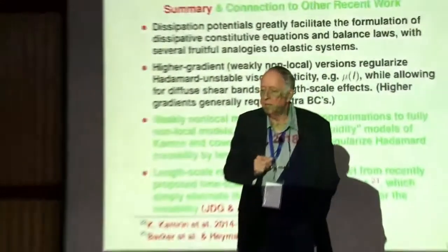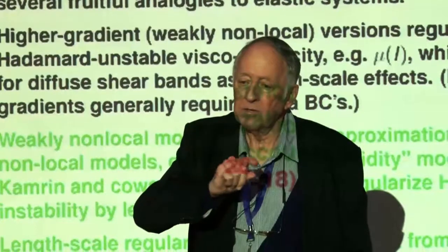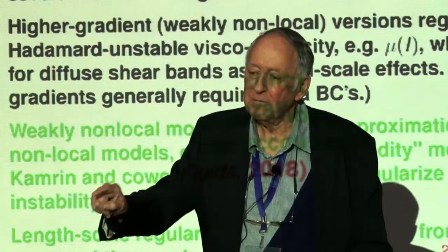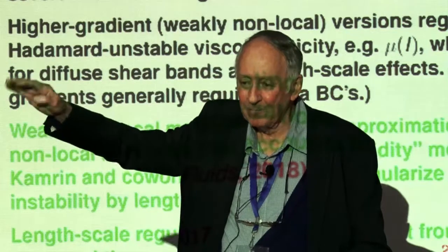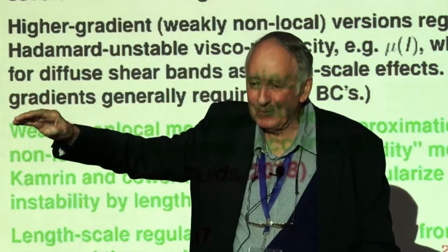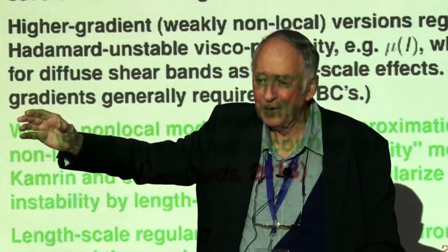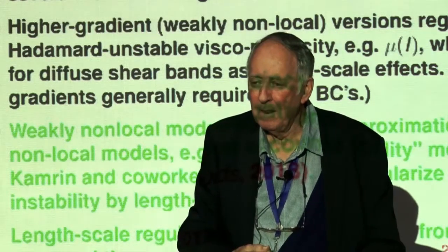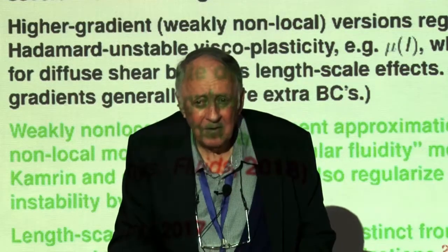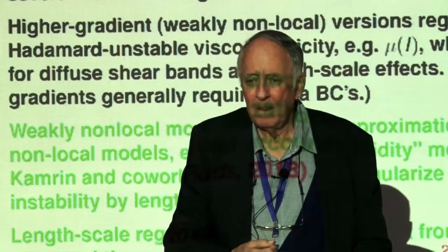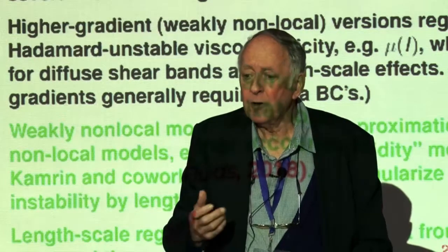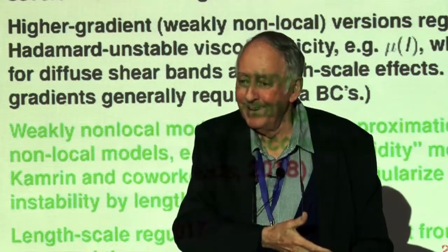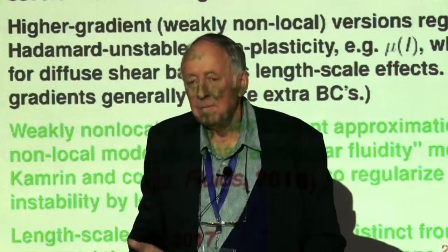Yes. No, it's not. Well, there's two sort of yield stresses. There's one in the mu of I model. There's a limiting lower friction coefficient and a limiting higher, and both are important. Both contribute to the instability because they involve regions of constant mu, and that's where the problem comes, where the friction is constant. So if I don't have a constant mu, then that instability is not there, right? Right. That's the trick these people use to put in viscosity. They let mu depend on I everywhere. So it's viscous stabilization.